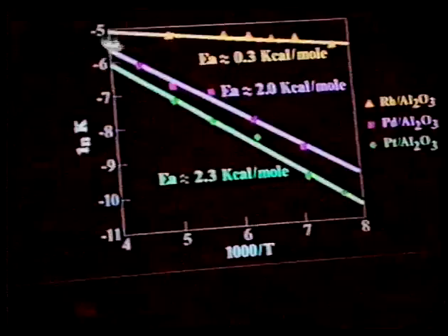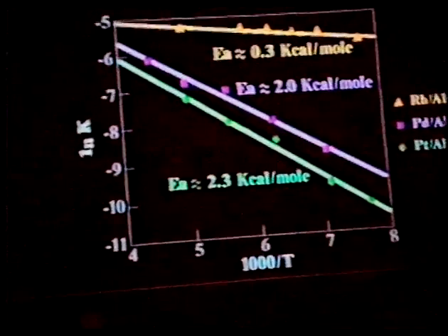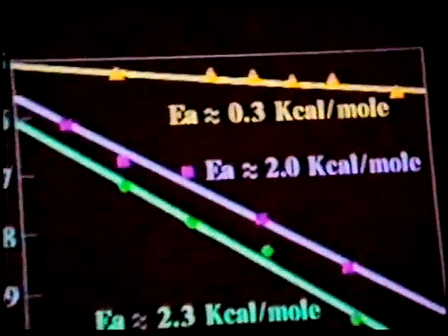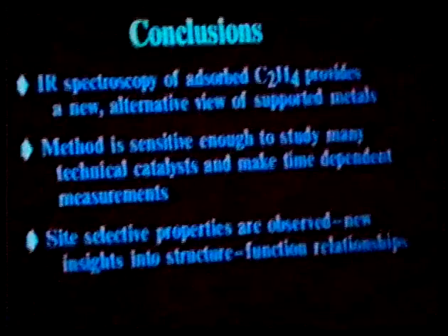However, the rhodium really likes to make ethylene. It makes it very, very rapidly at very low temperatures, and that's reflected in the very low activation energy for this process. So what I hope that I've showed you this morning is that we can use infrared spectroscopy of adsorbed ethylene, and that it provides a new and alternative view of supported metals.